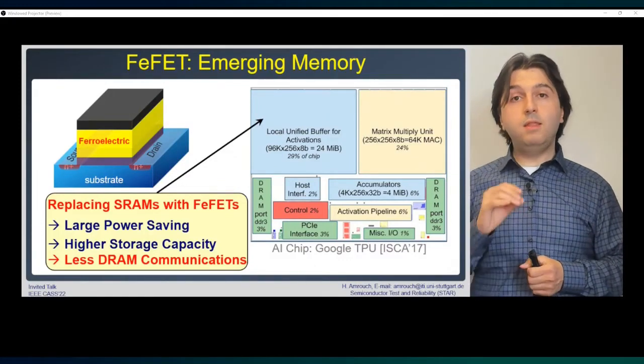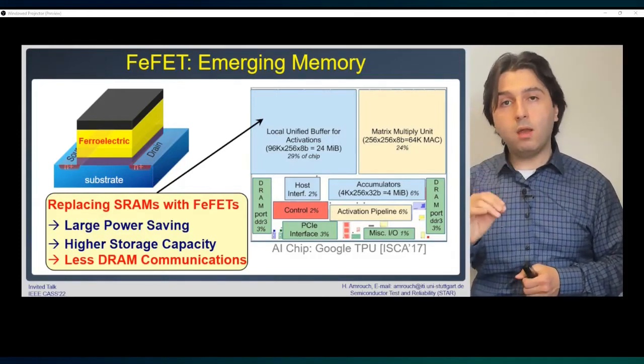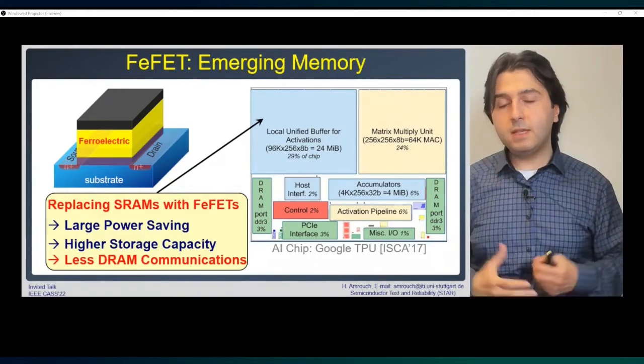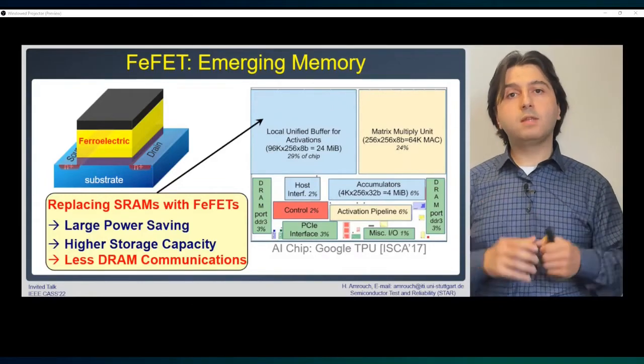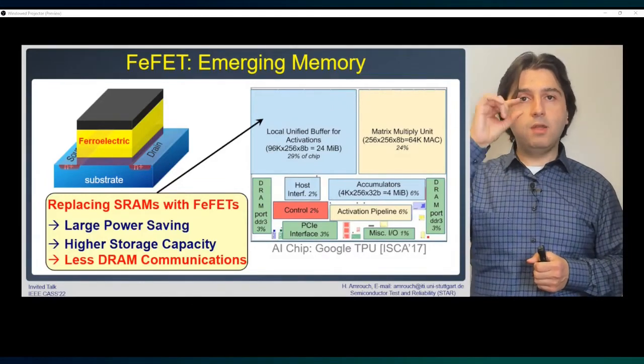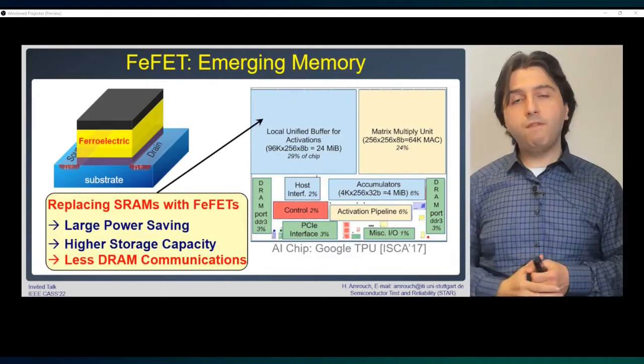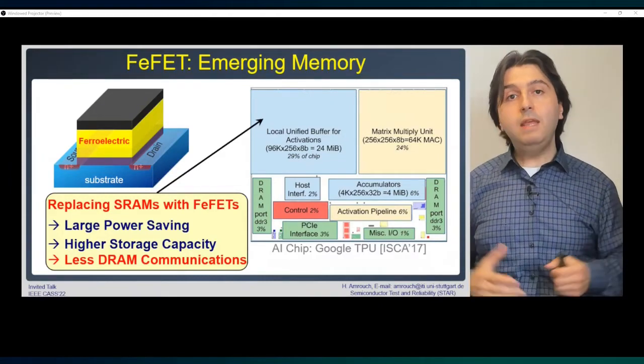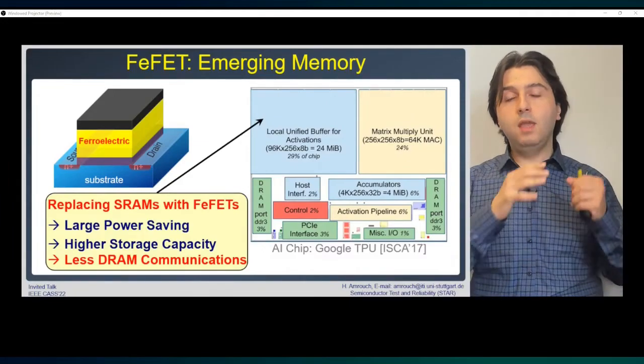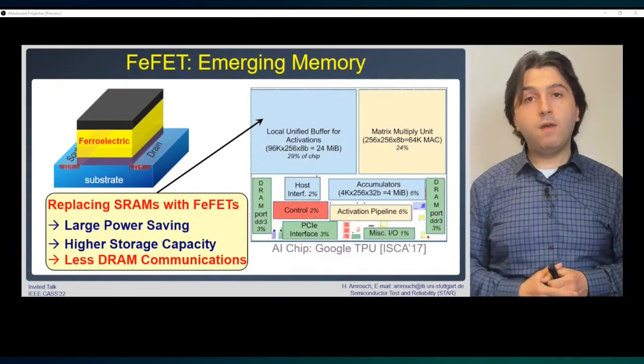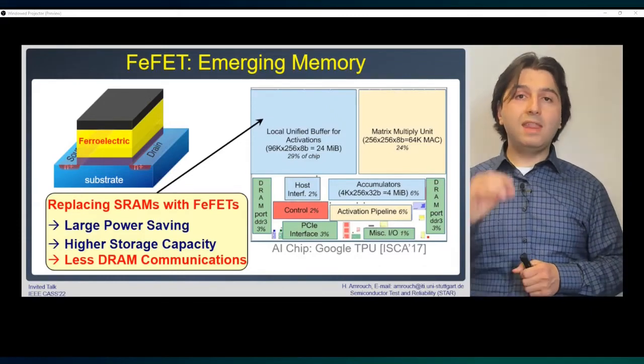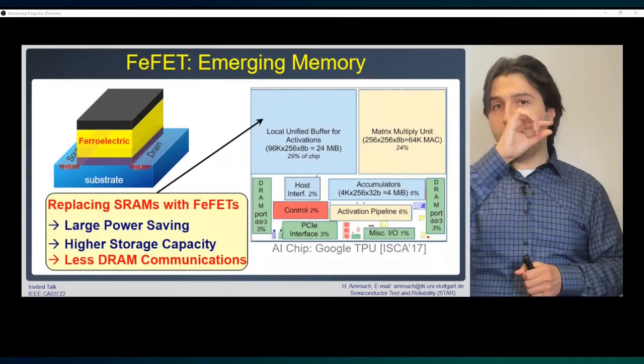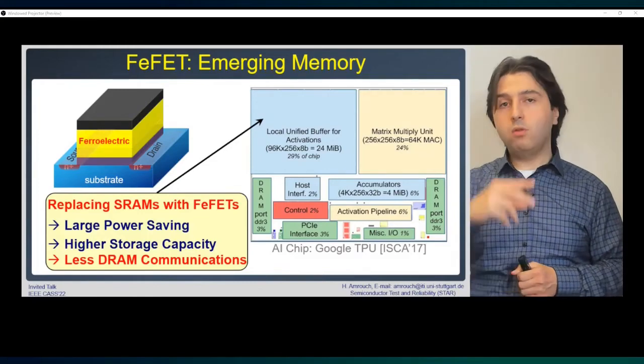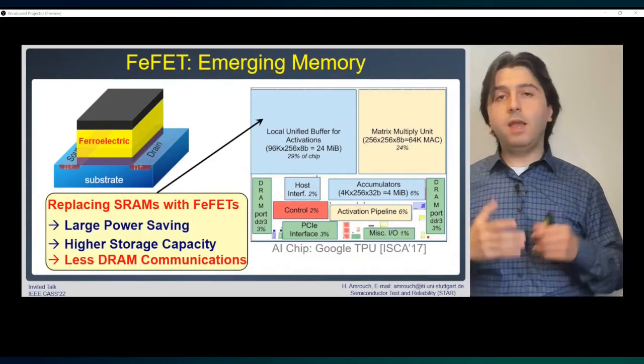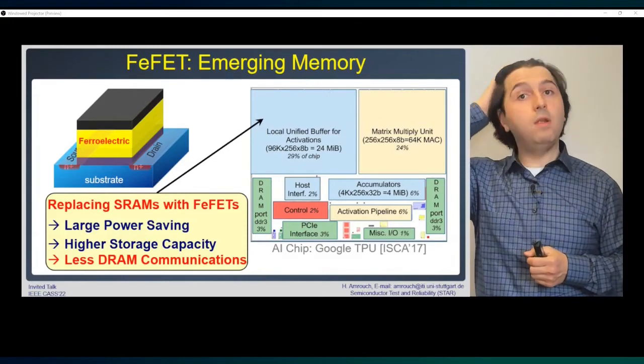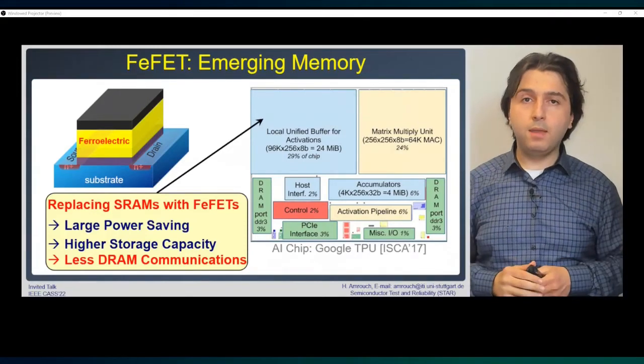This is indeed a breakthrough because it has been thought for a long time that it's impossible from a physics perspective to have a ferroelectricity effect under a certain thickness, when the layer becomes very, very thin. It has been believed for decades that ferroelectricity cannot be realized. However, very recently, as I said, they showed that at a thickness of 0.5, which is like a 2D layer, like two sheets of atoms, they are still able to realize ferroelectricity, which is indeed a big breakthrough.